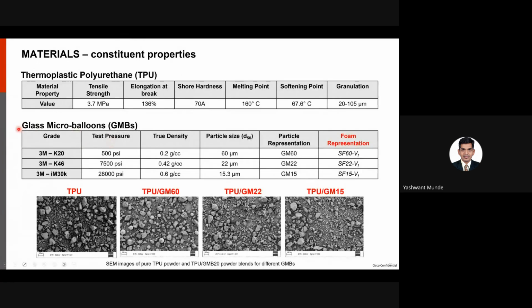And then we embed glass microballoons, GMBs is what I'll call them hereafter. We chose 3 grades of GMBs with different sizes and crushing pressure, as shown here. The particle size reduces essentially. We go from 60 micrometer of mean particle size to 22 to 15.